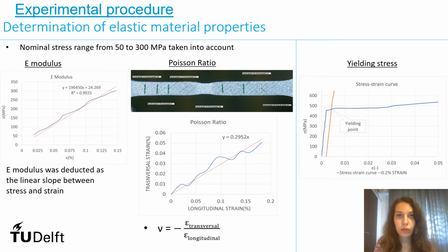For the elastic material properties, I determined the E modulus, Poisson ratio, and yielding stress using a nominal stress range from 50 to 300 megapascals, and for the E modulus and Poisson ratio, the classic methods for determining the properties. For the yielding stress, I computed a 0.2% strain with the slope of the elastic modulus, and at the intersection of the 0.2% strain and the stress-strain curve, I found the yielding point.